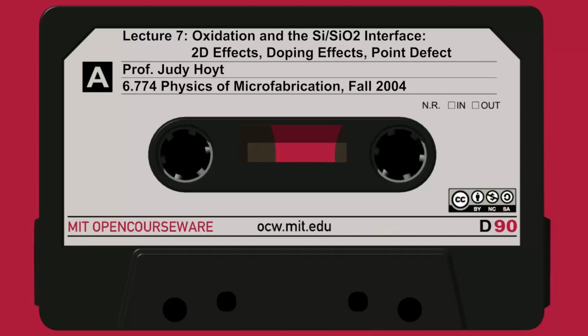So they have some default values, but people typically modify them as needed to fit the shape that's observed experimentally from LOCOS or from a pillar or from your structure. In practice, this number V sub S ends up being 0, which essentially means people believe that the solubility is not dramatically impacted by the stress. And so this extra term here, e to the P V_S over kT, goes to 1. And so people generally believe it's the K sub S and the D that are being modified by the stress.